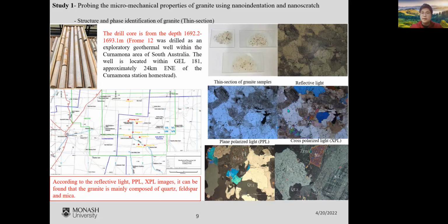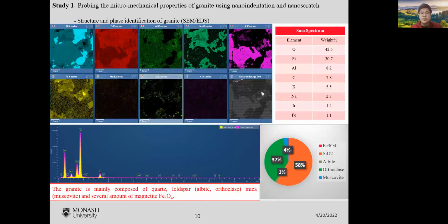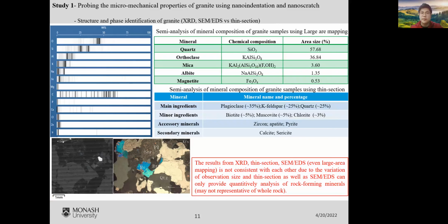Apart from the XRD, both the thin section test as well as the SEM-EDS test were also carried out, and we compared the results from these three tests. It is found that the results are not consistent with each other because of the observation size.